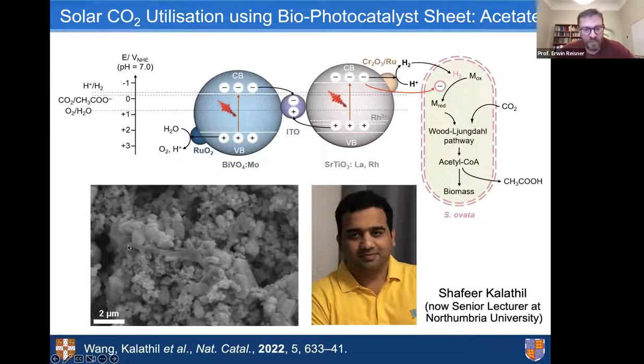And it's nice to see that these long rods here are the bacterium, and it really preferentially grows on the strontium titanate, so exactly where the hydrogen is being generated. Because the strontium titanate are the small particles and these larger blocks here are the bismuth vanadate. So this is this SEM image of this system.